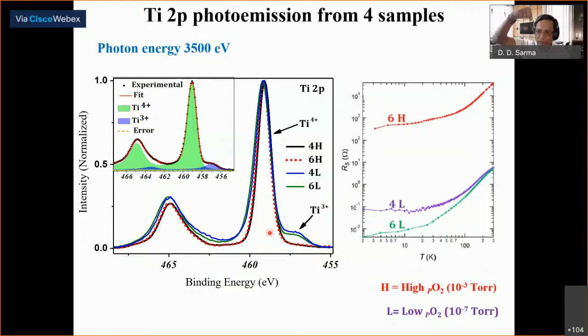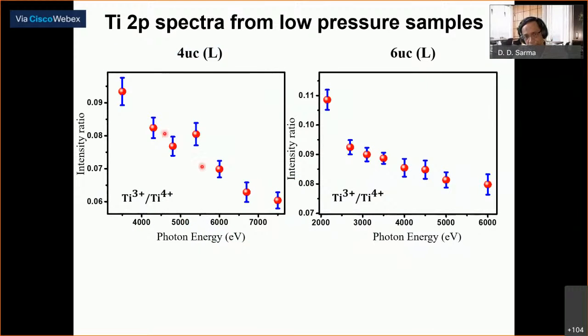That means as I increase the photon energy, I'm looking deeper down and trying to figure out this titanium 3+, is it at the interface or is it below? Where exactly is the titanium 3+, that electron that makes the system conducting? How is it distributed in this heterostructure? And that is what we are going to do next. And these are the experimental data points of titanium 3+ to titanium 4+ for two different samples. One is a 6 layer and the other is a 4 layer.